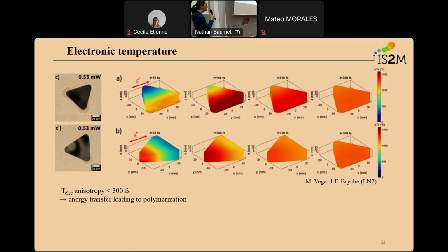It's a free radical polymerization, so we cannot control this, but we have many layers of monomers. As soon as you have one thermal initiator which will break, you will start to form many polymers. So you cannot have 1 nanometer or less of polymers. It's difficult due to the free radical polymerization system. Okay. It's really hard to constrain below 1 nanometer. Okay, thank you.